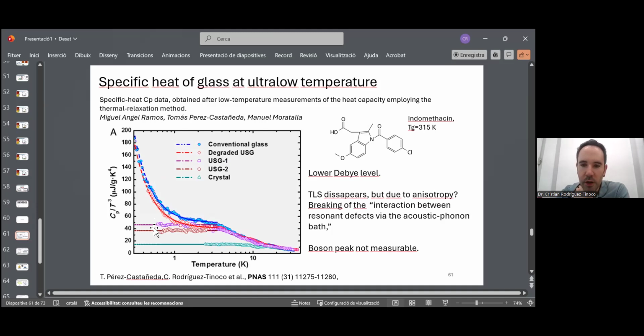At this point, we concluded that this elimination of the two-level system was due not to the density, but to the stability, but to some kind of anisotropy. Okay, remember, we have this anisotropy in the case of the ultrastable glass.